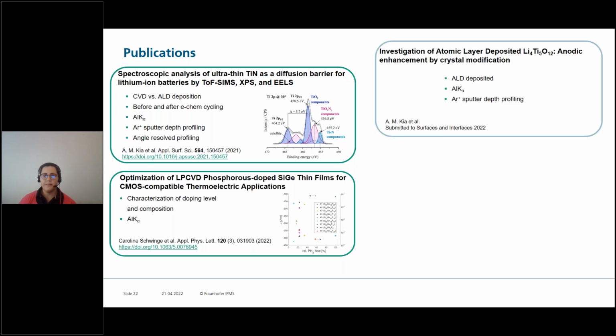We have a paper that we just submitted last week where we investigated atomic layer deposited lithium titanium oxide, commonly known as LTO, and this is normally used in solid state batteries as an anode. What we looked at here is that we did ALD deposition. We also looked at how the composition changed depending on the different deposition parameters that we used. And here we're really focused on argon ion sputtering and aluminum Kα as well.